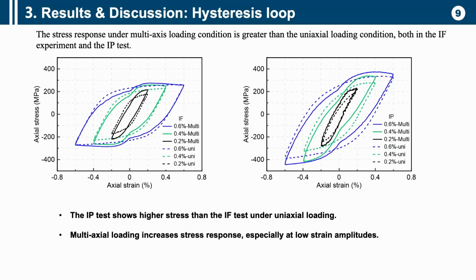Then we compare the hysteresis loop for uniaxial and multiaxial loading. The left is an IF test, the right is an IP test. So we just compare the axial stress. You can see for the IF test, for the small strain range, there is a big difference between the uniaxial and the multiaxial.